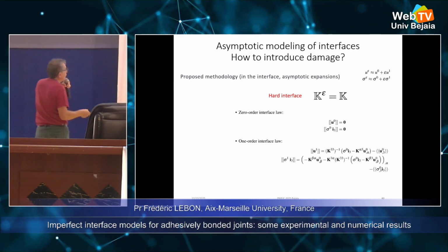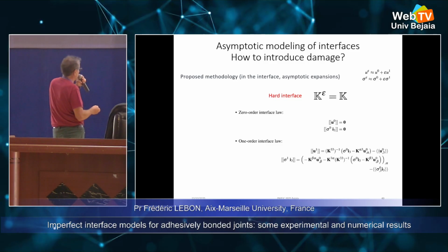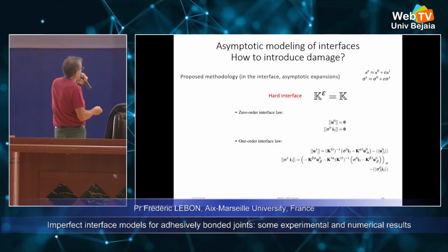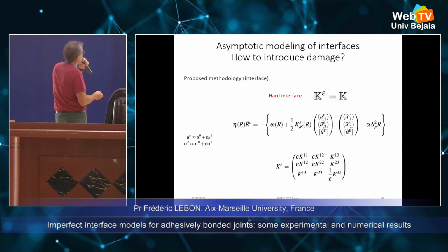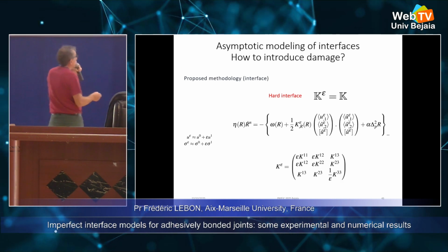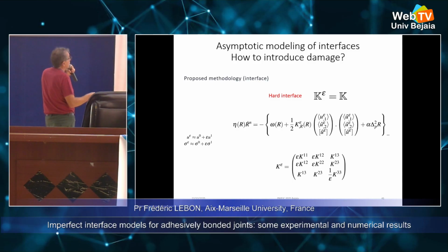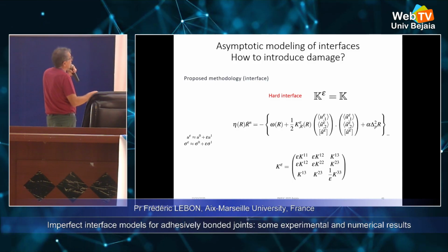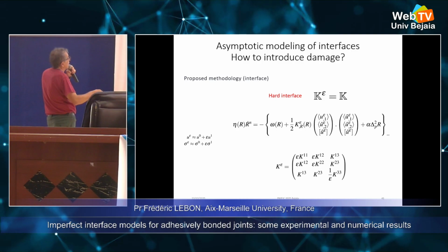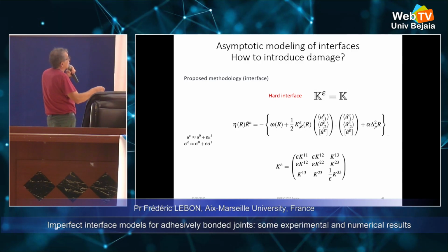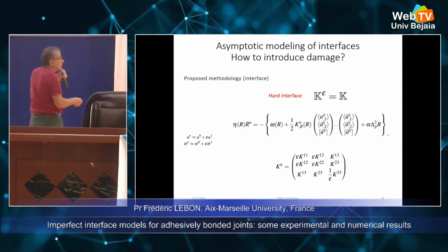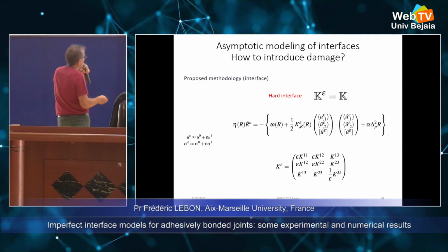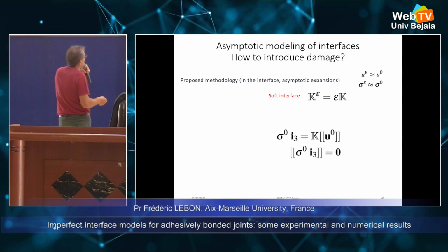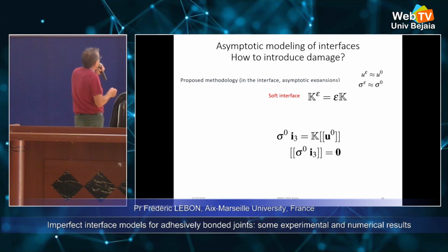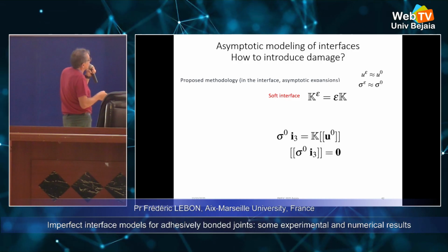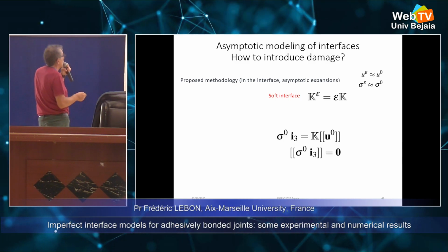something which is quite complex in terms of jump in displacement and jump in stress. And we have this kind of evolution law, which depends, in fact, on the jump in the displacement along the interface. And here there is not the jump, but the average of the derivative. So you obtain some tangential terms. The methodology for soft interface is, for me, quite more interesting.